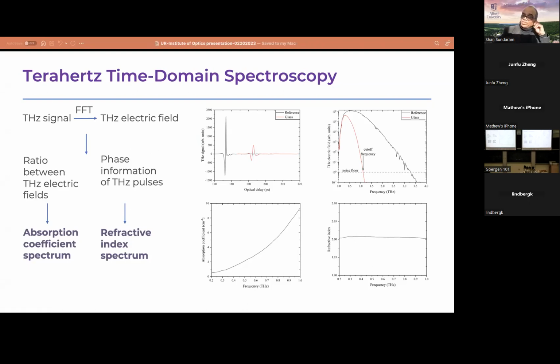I want to point out the noise floor. Often our spectrometer can go up to even 4 terahertz, but really the sample dictates how much we can measure: the sample chemistry and the sample structure. So often we hit the noise floor between 1 and 2 terahertz. So you would see our measurements are limited to that range, beyond which we could not differentiate the noise between the measurements.